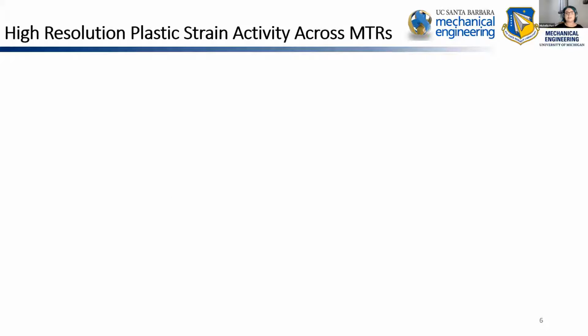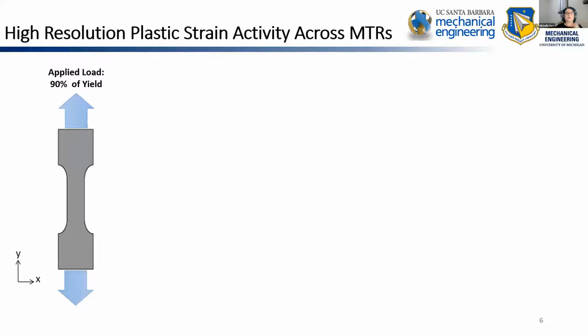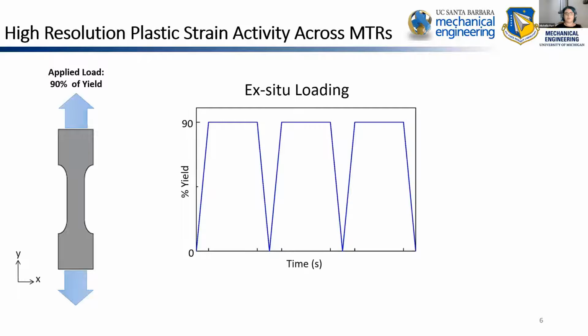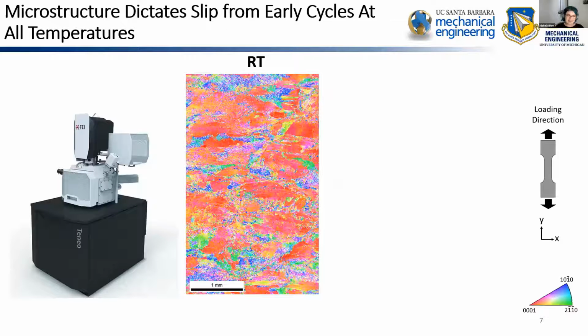So the experiments that I've run use dwell fatigue samples that have been cut out of a highly microtextured titanium material, which are then loaded ex situ with that trapezoidal waveform dwell fatigue loading form that we were discussing. And then after a predetermined number of cycles, the sample is fully unloaded from its load rig and then carried delicately over to an SEM and placed inside so that I can collect digital image correlation data over the entirety of the gauge section of the sample.